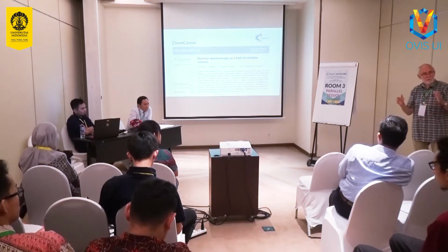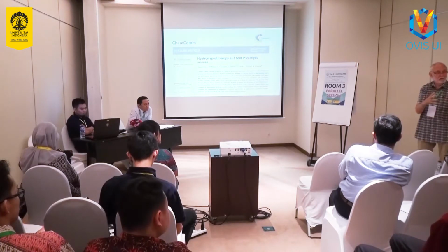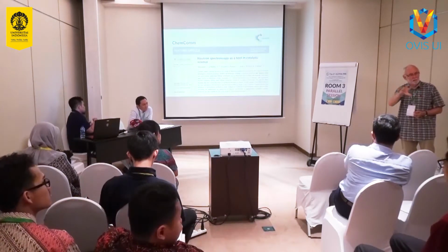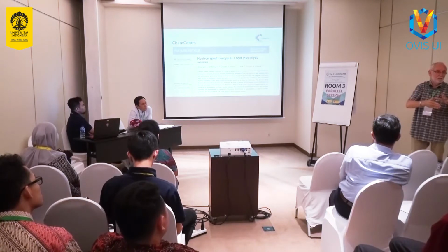And where we have a partly deactivated catalyst, we wanted to see how much methanol can still go in and be mobile. But it turned out, as you saw, that the methanol really doesn't like to move very fast in the zeolite at all. Even in the clean zeolite, it doesn't move. So it was the wrong choice. We should use a molecule like methane, which doesn't interact at all with the zeolite. Then we can study its mobility and learn how the presence of hydrocarbon deposits in the pores might slow the movement of methane through the zeolite. So it should be seen the mobility by using the hydrocarbons. Yes, for example.